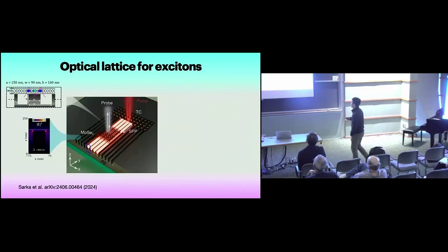Okay. So in the experiment, what we did is then to place a TMD right on top of this plasmonic structure. So I excite the system over here, and the surface plasmon propagates and imposes some spatially varying optical field on the 2D material. If I look at the simulation, this is a cross-section taking a cut like over here, and the electric field is actually very tightly confined to the corners of the ridges. So even though the ridge is 100 nanometers, the optical field is around 10 nanometers because of this antenna effect.